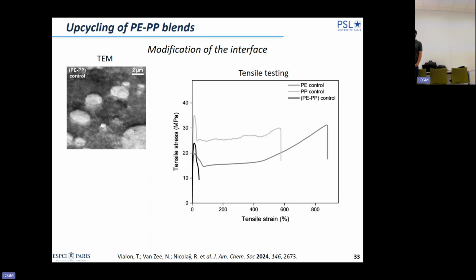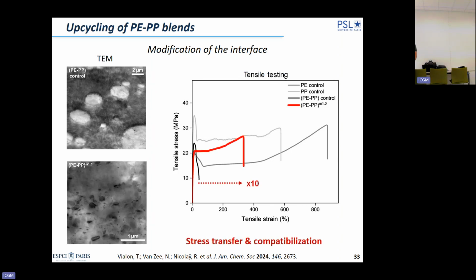Because if you do all of this and you don't have improvement of the tensile properties, it was pointless. So here you have the starting PE, starting PP. This is a blend of the two without modifier. And when we do the reactive processing, we go back to a ductile material. It is crosslinked, so we don't expect to have the same ductility. But we go back to a material which has an elongation at break higher than 300%. It's an improvement of a factor of 10, in fact, more than 10 if you compare to the unmodified sample. And we really go back to a material which has very good mechanical properties.